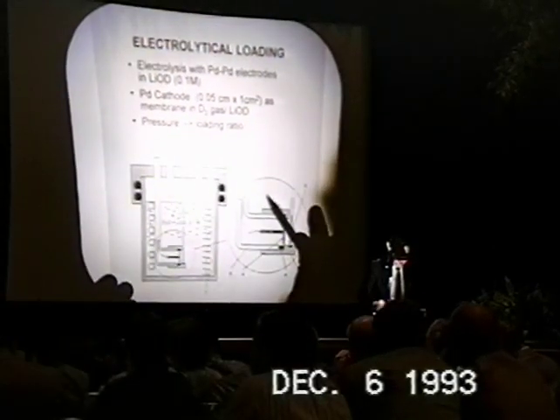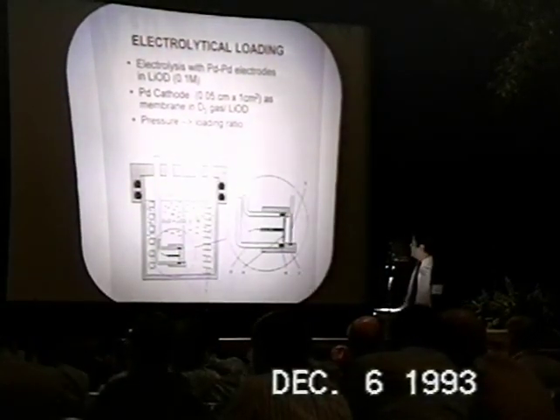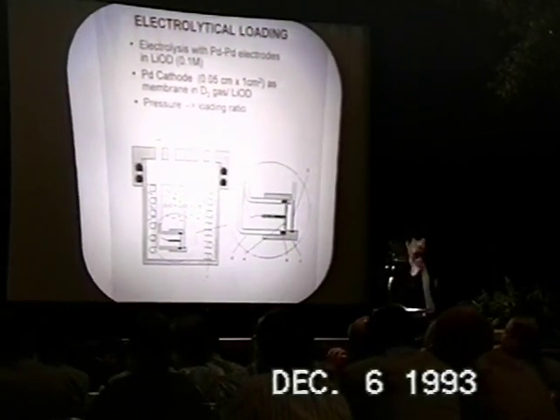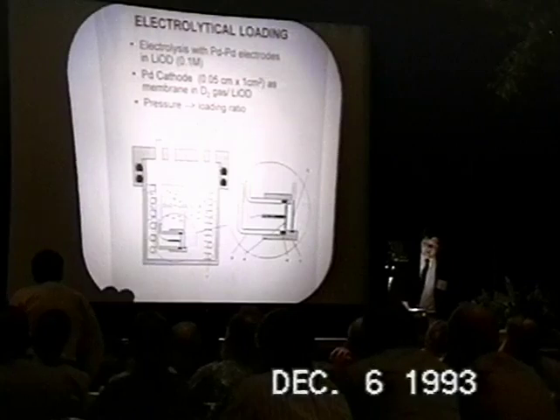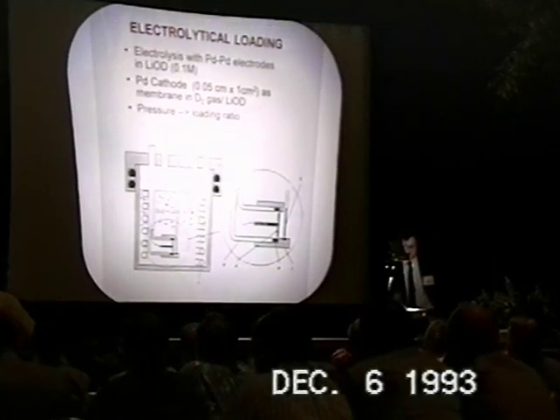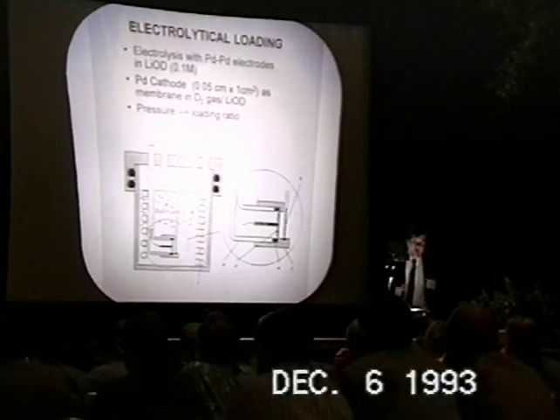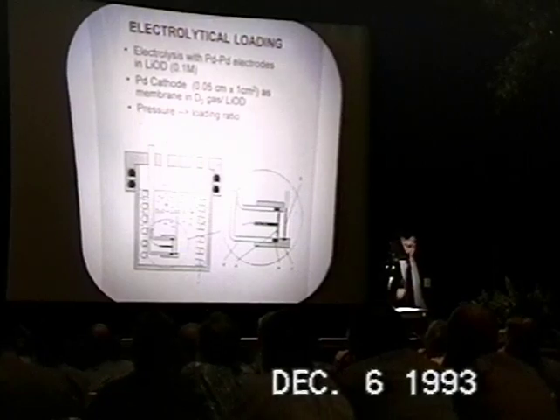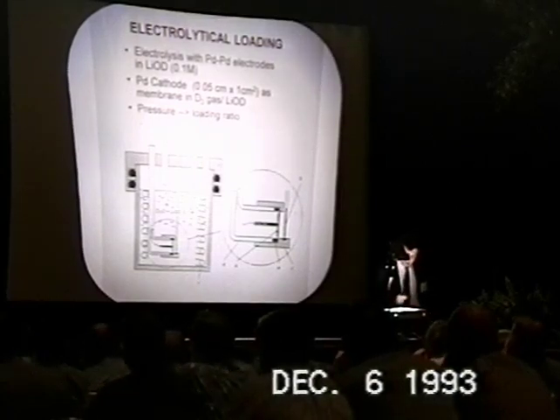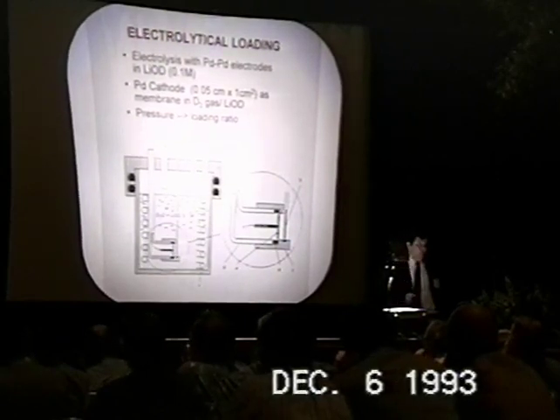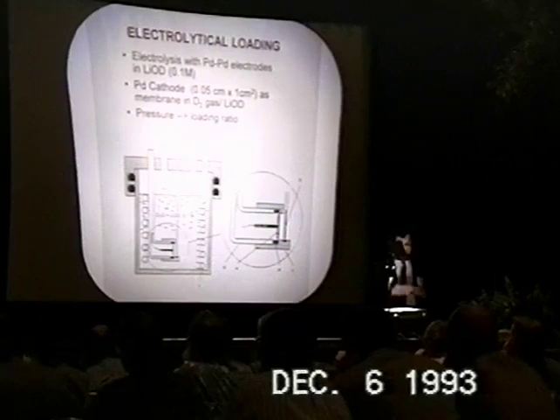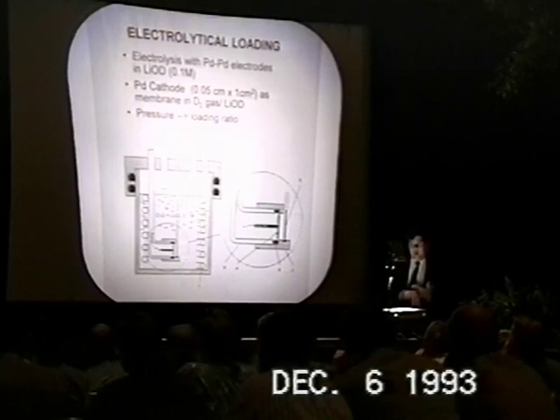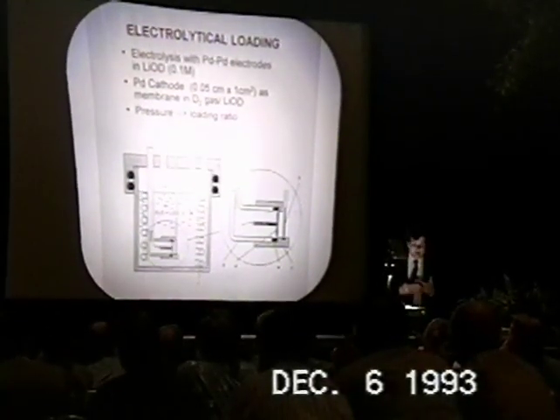Well, just a few words, a few minutes on our approach. As I told you before, we are quite interested in the electrolytical loading. For this reason, we make electrolysis with palladium electrodes in a solution of LiOD 0.1 M. We use palladium electrodes in order to regenerate on the surface of the cathode a new sheet of palladium. In such a way, we can avoid contamination, pollution, and so we have always a new surface.